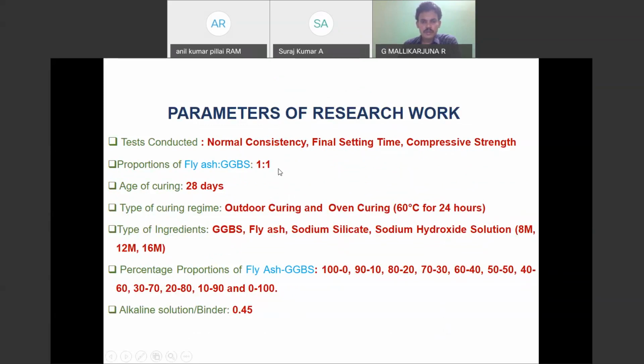Currently, we are seeing parameters for research work. Yes, sir. The ingredients considered are sodium hydroxide and sodium silicate, and for the different concentrations of sodium hydroxide, we considered 8 molar, 12 molar, and 16 molar. The proportions of fly ash and GGBS we varied from 100-0 to 0-100, and the alkaline to binder ratio we kept at 0.45.